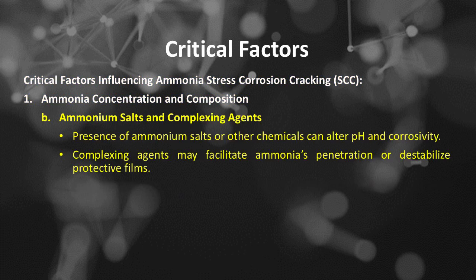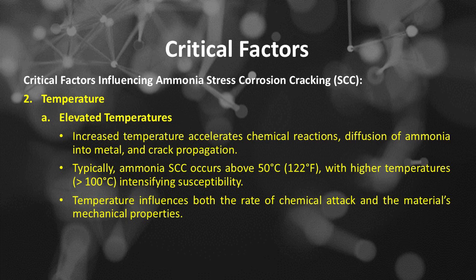Number B, ammonium salts and complexing agents. Presence of ammonium salts or other chemicals can alter pH and corrosivity. Complexing agents may facilitate ammonia's penetration or destabilize protective films. Critical factors. Number 2 is temperature, which includes, number A, elevated temperatures. Increased temperature accelerates chemical reactions, diffusion of ammonia into metal, and crack propagation.